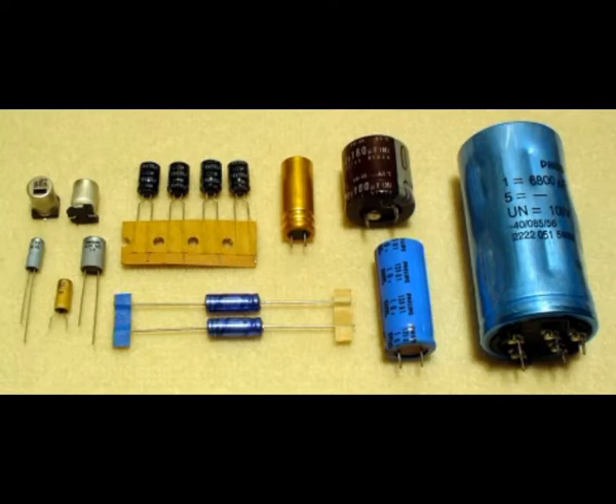The electrochemical oxide-forming processes take place when voltage in correct polarity is applied and generates an additional oxide when transients arise. This formation is accompanied with heat and hydrogen gas generation. This is tolerable if the energy content of the transient is low. However, when a transient peak voltage causes an electric field strength that is too high for the dielectric, it can directly cause a short circuit.